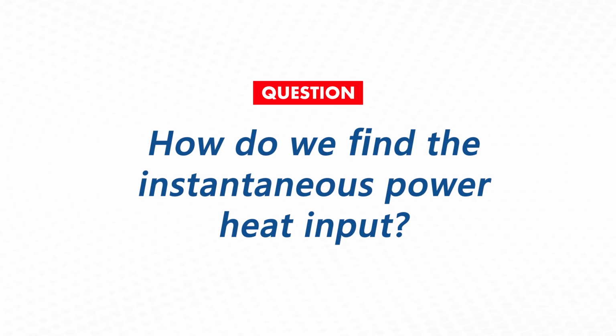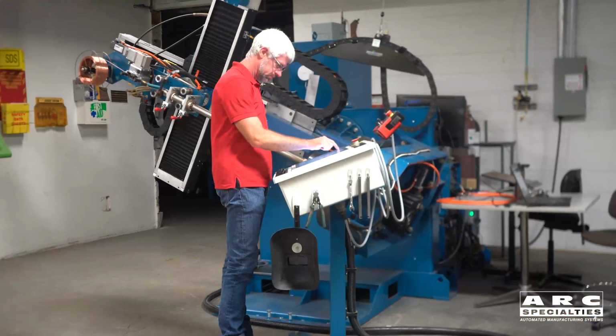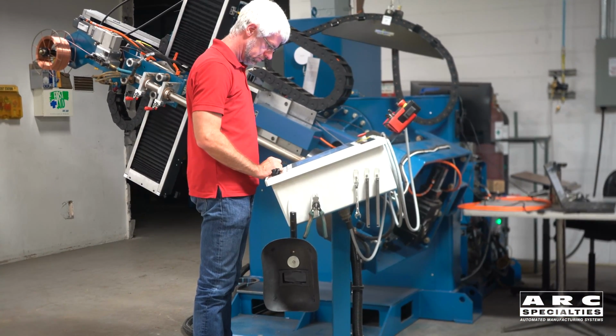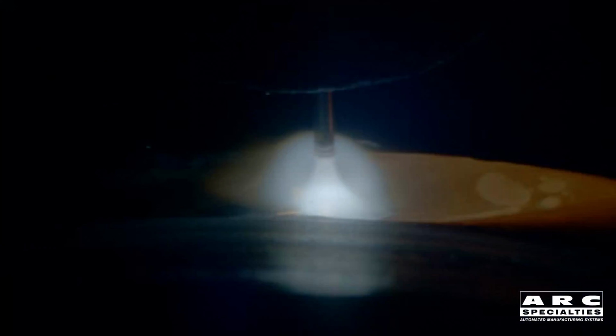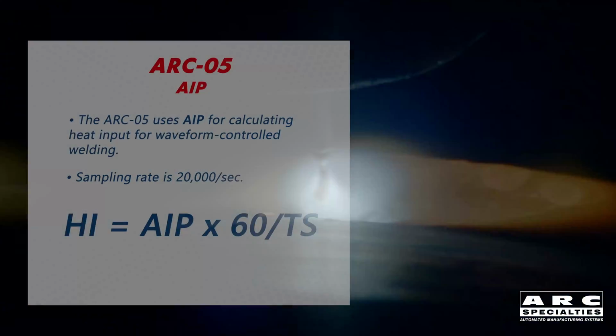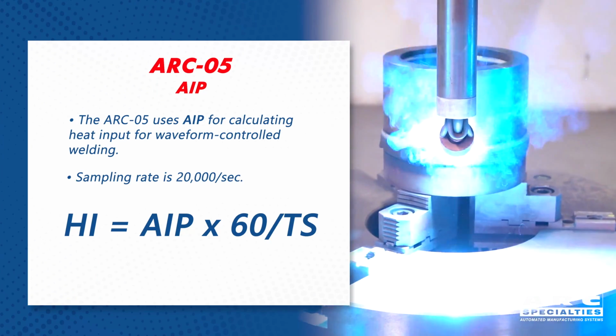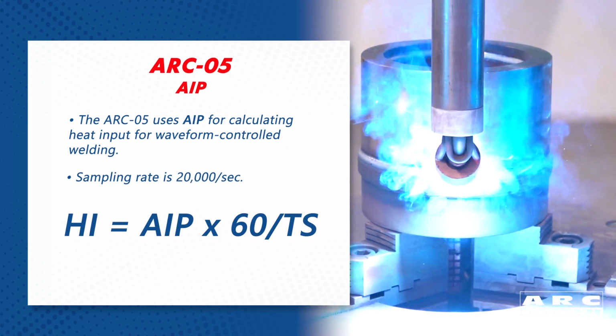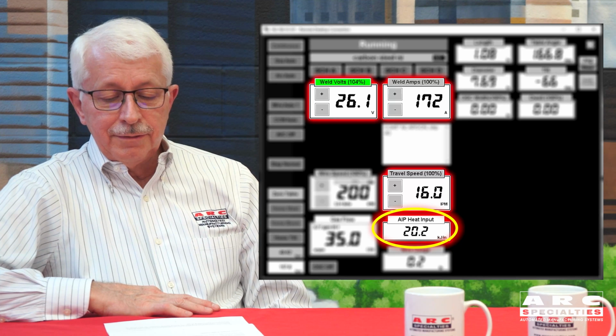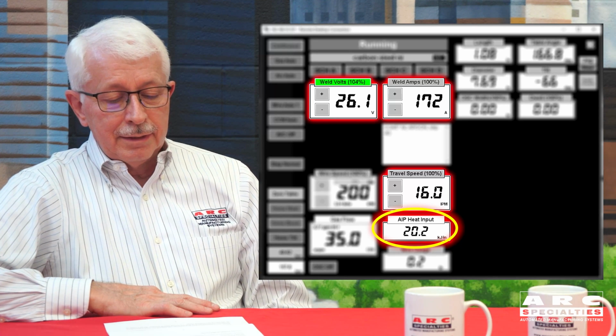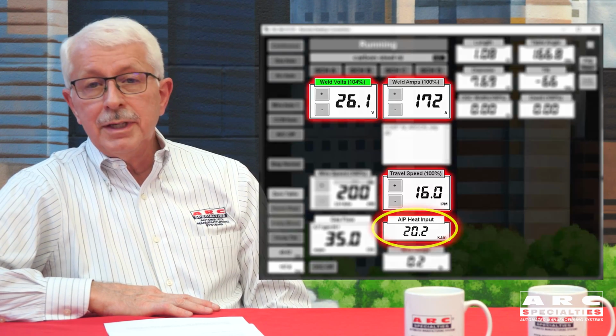So how do we find the instantaneous power heat input? For average instantaneous power calculations, or AIP, we're using the average of the products of amps times volts at a sample rate of 20 kilohertz, or 20,000 times a second. And we know our travel speed, so we know time and distance. So we plug it into the formula for our calculation. So looking back at the HMI operator screen, if I toggle the heat input button, I get average instantaneous power heat input. So that's how we calculate heat input using the old conventional formula, and how we do it using the new average instantaneous power formula.